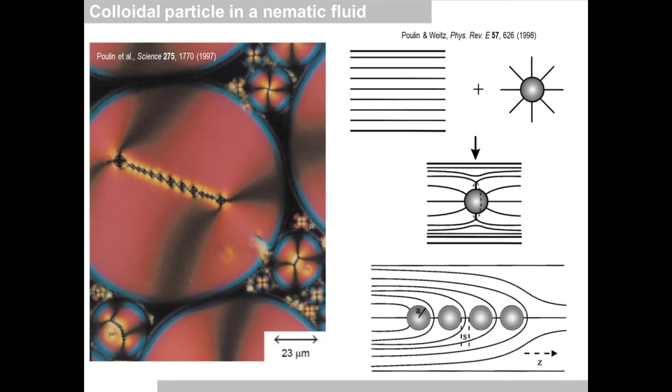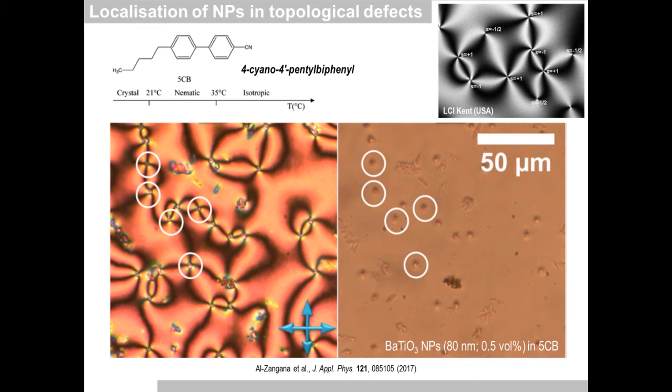Poulin and Weitz have shown that this defect formation would assemble the suspended particles to minimize the deformation energy of the medium. Different from the perfect nematic alignment, when the nematic liquid crystal material, like 5CB, is confined between two glass substrates, the heterogeneous planar orientation of the nematics results in the Schlieren texture under the crossed polarizers.